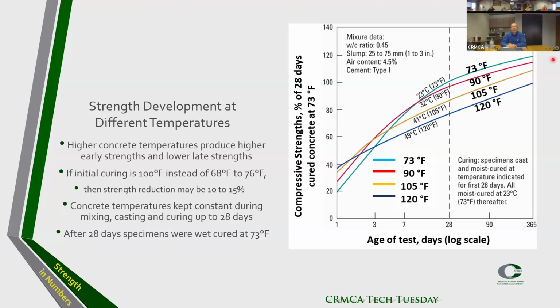What we see in this case, if we go from 70 to about 100 F, we reduce the strength by 10 to 15 percent. This goes back to what JT and Mike talked about a month ago, curing of cylinders. If you cure your cylinders out in the sun at 100 degrees, don't expect good 28-day strength. It's going to be low. They need to be cured at the defined temperature range.